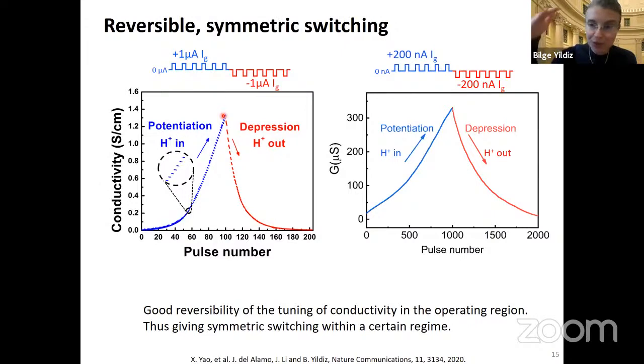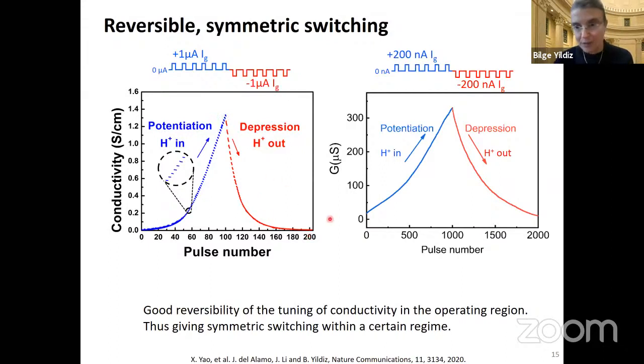You're causing permanent changes in the conductance, or in the strength of the synapse. And by reversing my environment, by reversing my polarization, we can pull out the hydrogen and depress the synapse, weaken the synapse. So we can capture both the potentiation as we insert hydrogen and depression, or depotentiation, as we extract hydrogen out of the channel material. And it gives us very good reversibility of conductivity, symmetric potentiation and depression, which is desirable for using them as inorganic synapses.